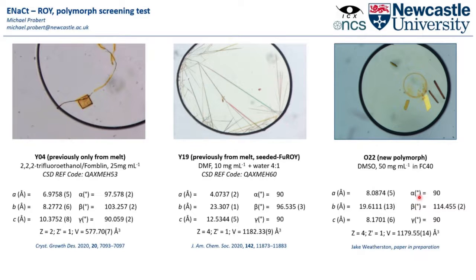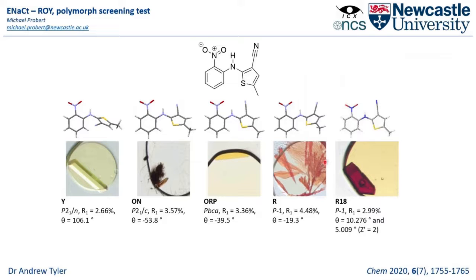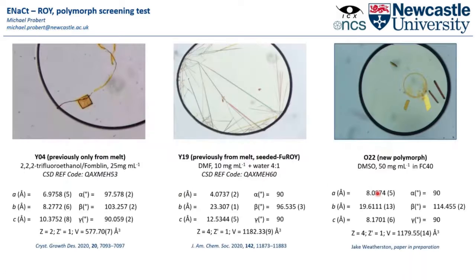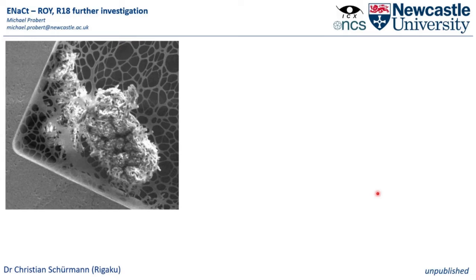So if we just circle back to that R18 form, this one here, this turns out to be highly metastable, and this is where I just want to highlight that using those techniques we described earlier can be particularly beneficial. So that R18 form can undergo a transition either by pressure or temperature stimulus and goes to a predominantly amorphous phase. And this is an SEM image of that amorphous phase, and you can see, although the majority of this is amorphous, there are rod-like crystals growing out various places.